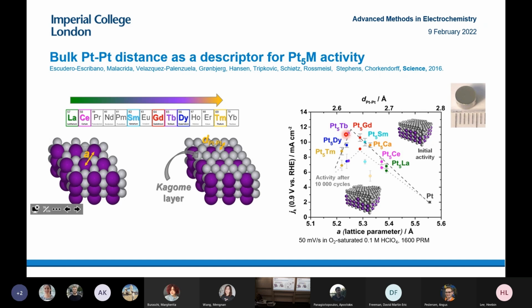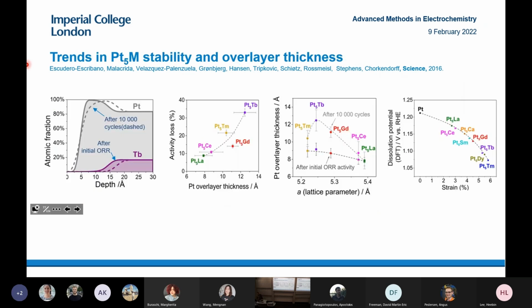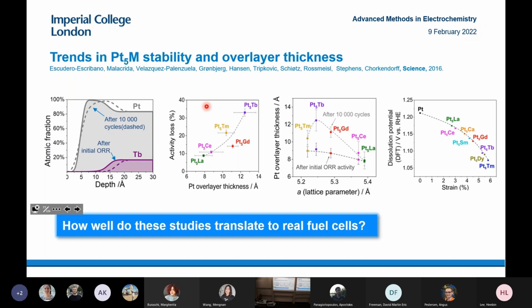We actually think it's not really a proper volcano. What we think is actually happening is that when you go too far, the strain collapses, and you no longer have the same strain as when there's a mild strain on the surface. If you think about it, the more strain you apply to the surface, the less stable it will be. So if you apply too much strain, it will collapse.